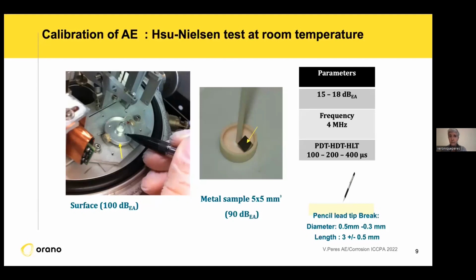The test is the Hsu-Nielsen test. We do it at room temperature, and we have to verify that the sound coming from the sample going to the top here, close to the piezoelectric system, is detected. So we do that with a pencil tip. We break it on different surfaces. We break it on the top, close to the piezoelectric system, and we also do it on the metal samples, in order to know that if we break the tip of the pencil here, we hear something at the piezoelectric after preamplification of the noise. And if we succeed, it's okay, we can begin the experiment.